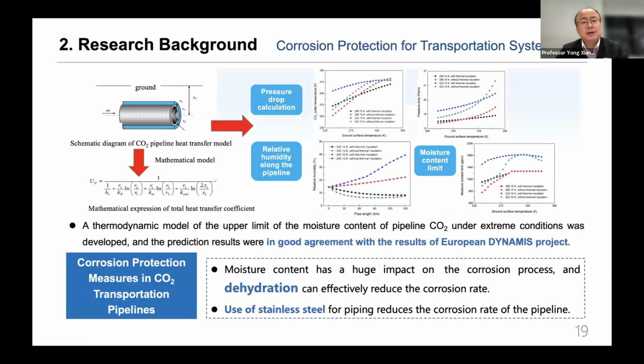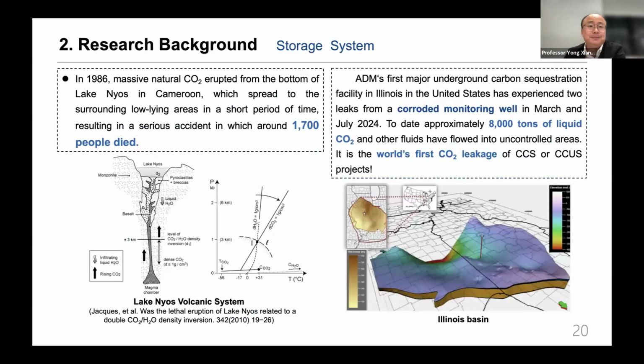So what is the conclusion for corrosion protection for the CO2 transportation pipeline? What we suggest is dehydration. You have to remove most of the water inside, then you can control the corrosion very effectively. Maybe below 500 ppmv, maybe 200 ppmv. Maybe in the USA they also have a standard for that, maybe 40 ppmv, like that. But if you have a lot of money, you can use stainless steel, like what happens in Norway. They use stainless steel for the CO2 pipeline. It can also control the corrosion.